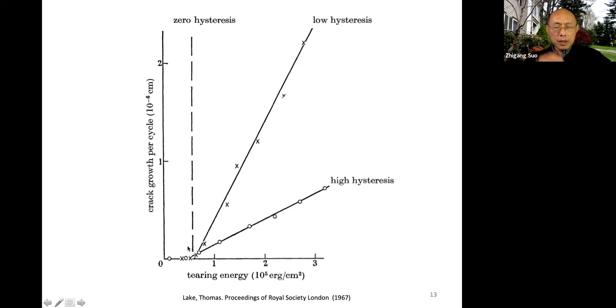So remember, for natural rubber, you have a potent hysteresis mechanism by crystallization, strain-induced crystallization, and when you reduce the strain, you melt. There's crystallization and melting. It is a wonderful material, right? This hysteresis gives you this enormous toughness, 10,000 joule per meter squared. Now, if you shut off all this melting, people do experiments.